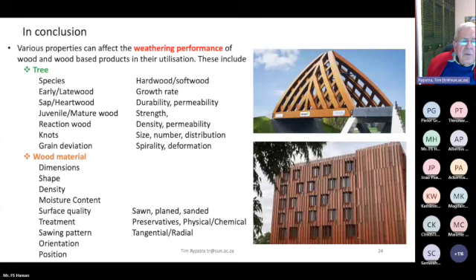So in conclusion, various properties can affect the weathering performance of wood, which is not very helpful and quite a challenge, but we know that species has an effect. The amount of early or late wood, in other words, the growth rate of wood, certain wood with certain growth rates weathers better than others. The presence of sapwood and hardwood. Sapwood is regarded as non-durable, and if moisture content levels remain high in sapwood, then you can get discoloration and later on more serious fungal attack. Juvenile or mature wood, which has a strength implication at least.